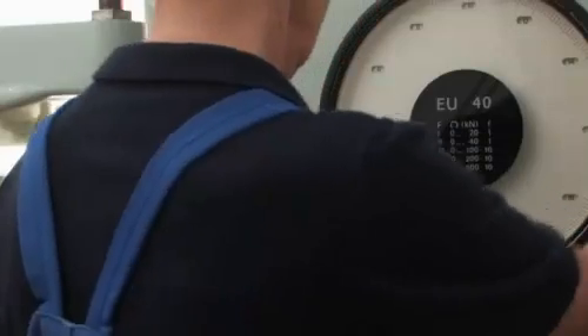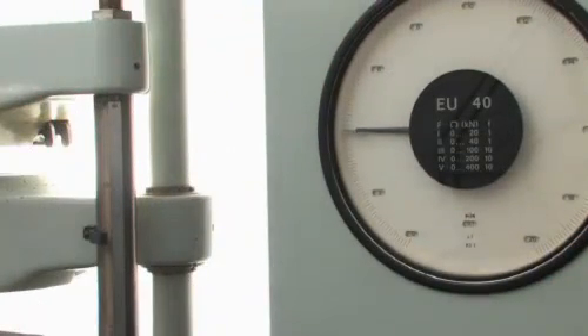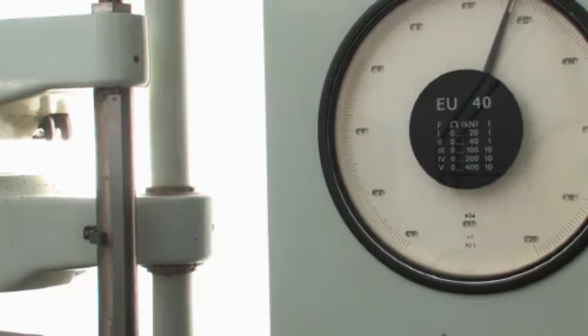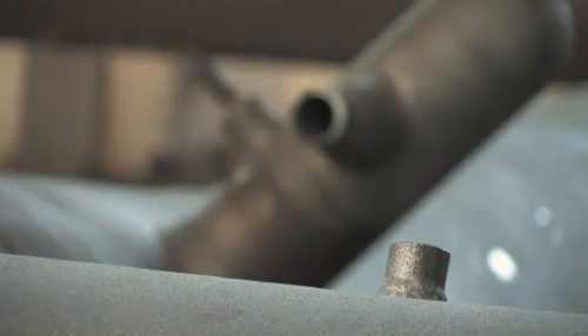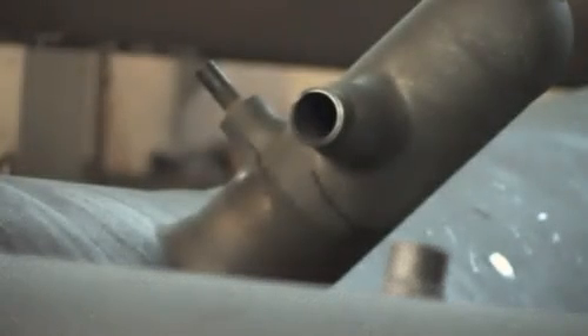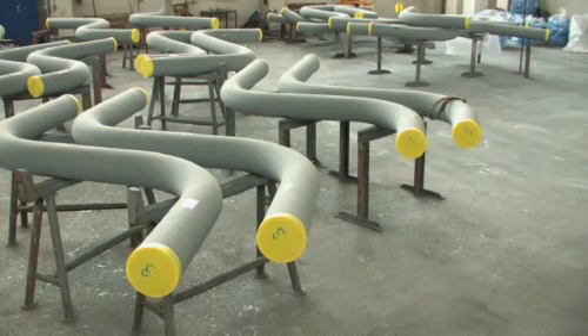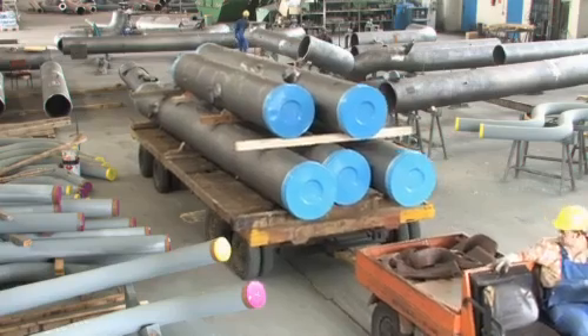Depending on the production standard and customers' requests, there will also be destructive tests carried out on material specimens from sample bands. They include, above all, tensile tests and notch impact bending tests at different temperatures. Metallographic tests serve for proving the correct metallurgical structure. Following the test and acceptance stages, the spool is then mechanically treated and finish processed. After sandblasting, an anti-corrosive coating is applied. Now the component is ready for dispatch.